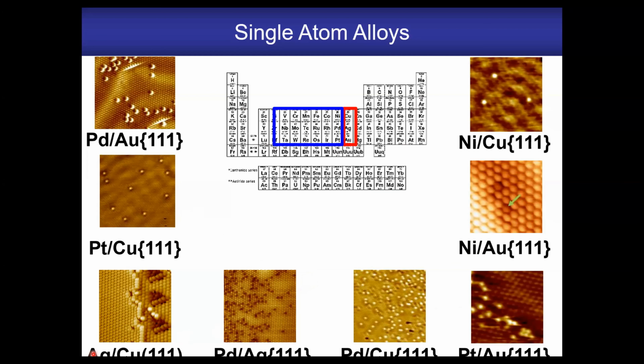Other combinations like silver copper don't mix too well at all, where you get mostly separated domains. And in this case of platinum gold, you actually see you've got both single atoms and small clusters. And it's really due to the mixing enthalpy, where the ones that form single atom alloys have a negative mixing enthalpy. So for example, nickel would rather be surrounded by copper than other nickel atoms. So the thermodynamics drives the atomic dispersion of these. Whereas, I'll show you later, platinum and gold have pretty much zero mixing enthalpy, which means the formation of single platinum atoms or clusters is equally preferred, and that's why you see a distribution of sites.